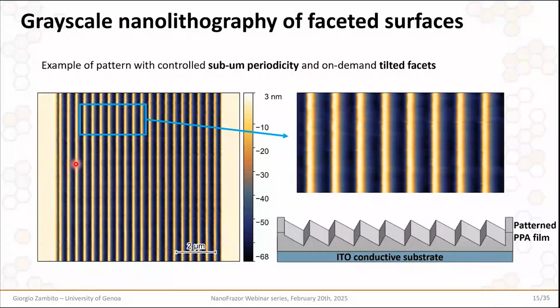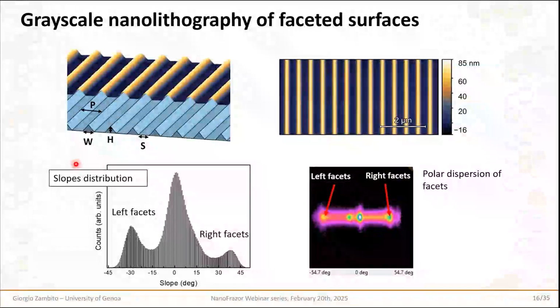So basically, we are able to obtain landscapes like this, where we decide a priori the tilting of the facets. For example, in this case, we have a 25 degrees tilt on one side of the facets, on the left side, and 15 degrees on the other side. What you can see from this image is that we have a really high reliability of the process, because what you see in light blue in the bottom part of the image is the design as it is fed to the NanoFrazor, while in the top part, overlaid, you see what we actually get through the imaging capabilities of the NanoFrazor, demonstrating that we are able to replicate these geometries with a very high reliability.